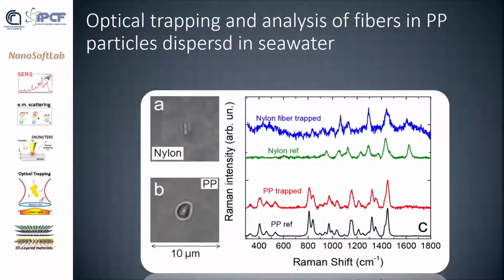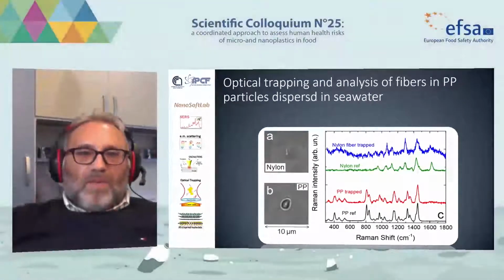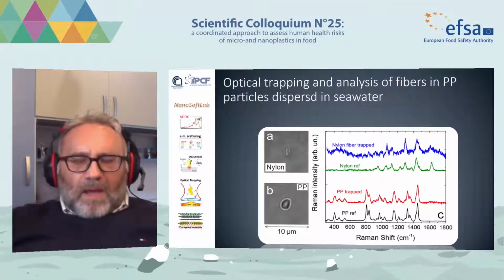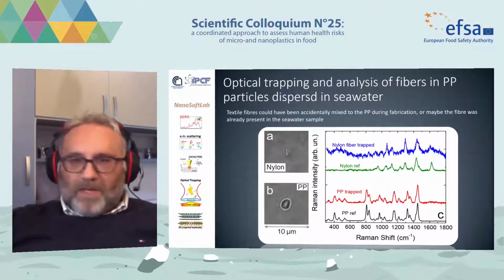We can also do this, for example, in a sample where we had some dispersion of polypropylene particles - the spectra down - and we can distinguish this from nylon particles that we discovered dispersed.